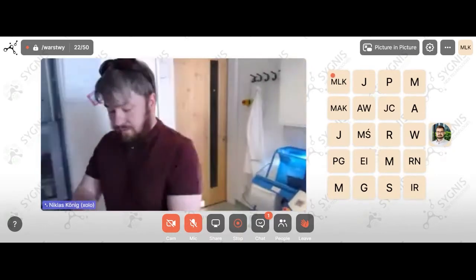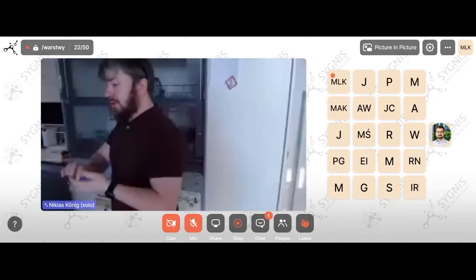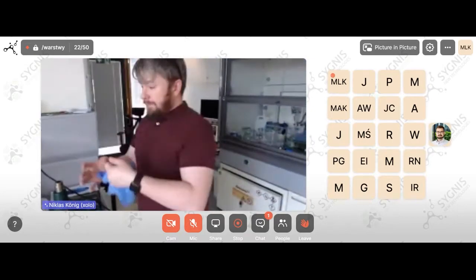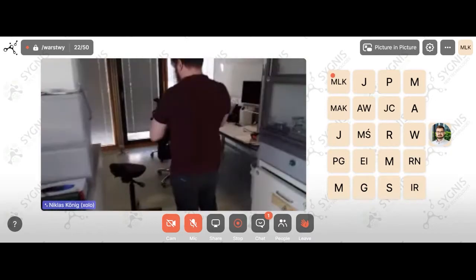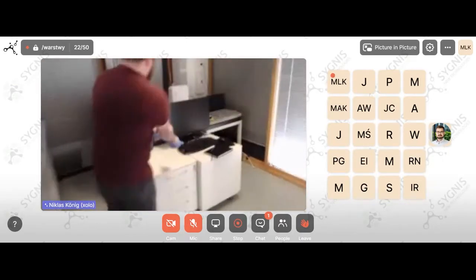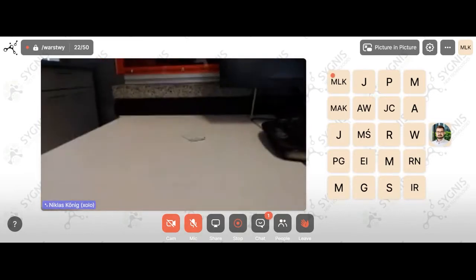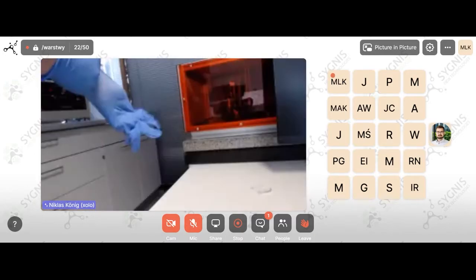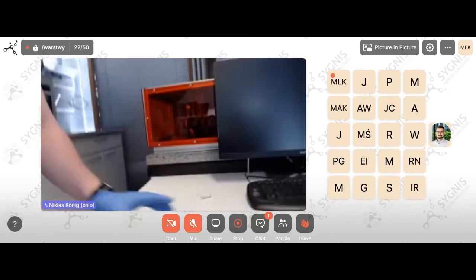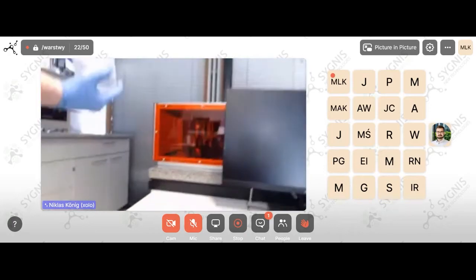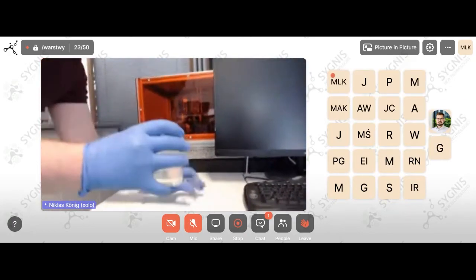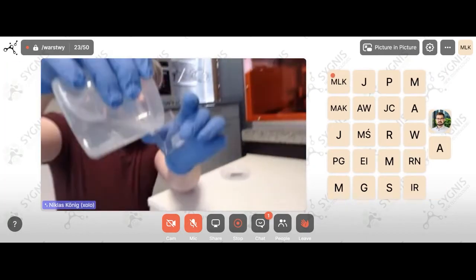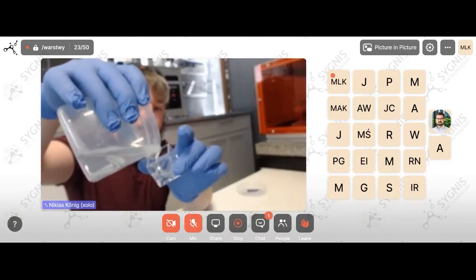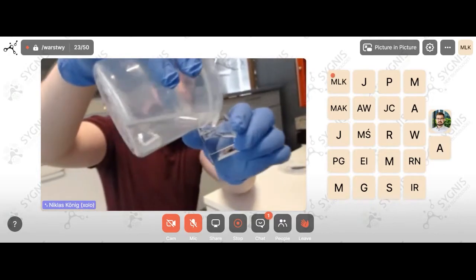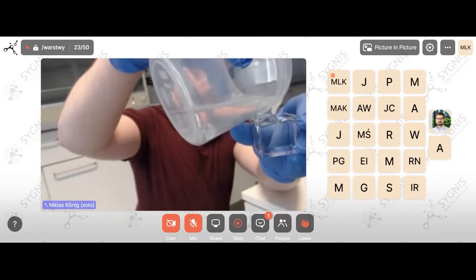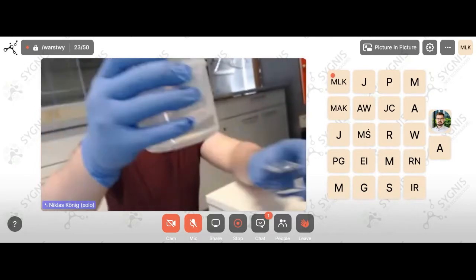And now we can go to the cuvette. We have prepared this resin before, just to cool it down and use it. Here we have the cuvettes. We have different sizes of cuvettes. Here's a 3 centimeter, and we also have 5 centimeter, 1 centimeter, and also the big 10 centimeter. But here's the prepared resin, the urethane methacrylate and the photo initiator. Here we fill it into the cuvette. Beautiful.